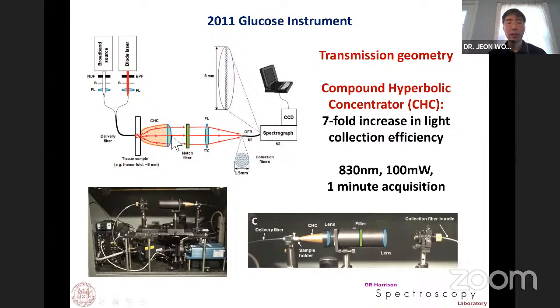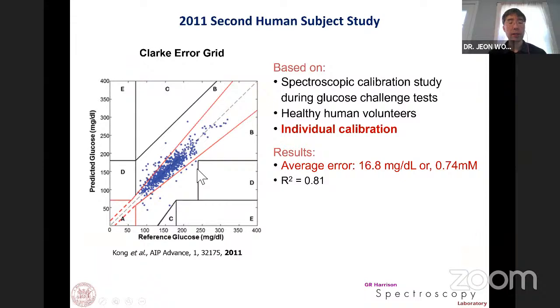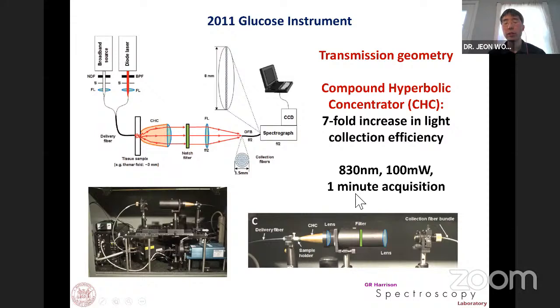By using this small, non-emitting optical element, we were expecting 7 times more signal from the simulation, but it is a real device. So after fabricating, we confirmed that it can still increase the system throughput by 5.5 times. Using this device, we could reduce the illumination power to 100 milliwatt, and also we could reduce the integration time to 1 minute. So these are the clock error grid, reference blood glucose concentration and predicted value. They are mostly in the linear region. And it has a similar accuracy, about 17 milligram per deciliter, with 1/3 of the power. Here it's 100 milliwatt, and 1/3 of the integration time, 1 minute integration.